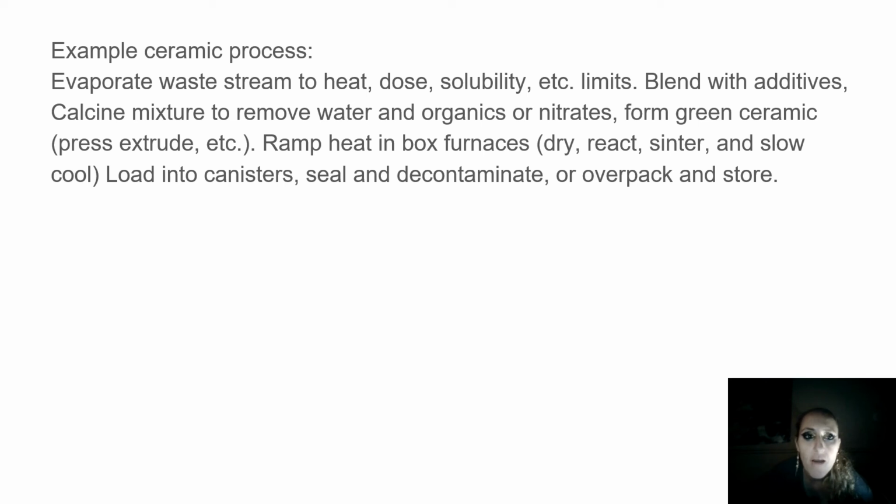Example ceramic process: evaporate waste stream to heat, dose, solubility, etc. limits. Blend with additives, calcine the mixture to remove water and organics or nitrates. Form green ceramic: press, extrude, etc. Ramp heat in box furnace: dry, react, sinter, and slow cool. Load in canisters, seal and decontaminate, or overpack and store.